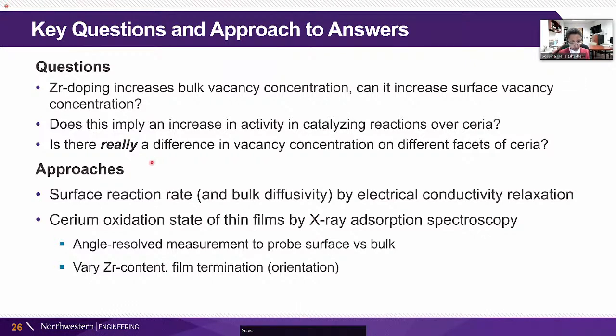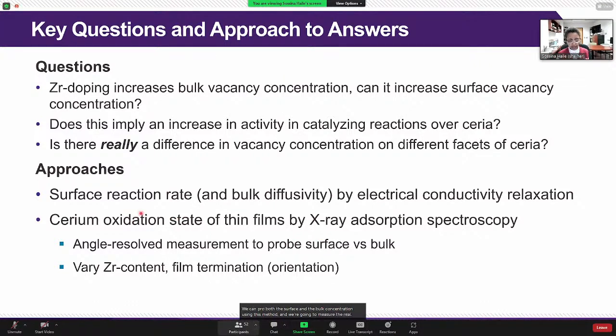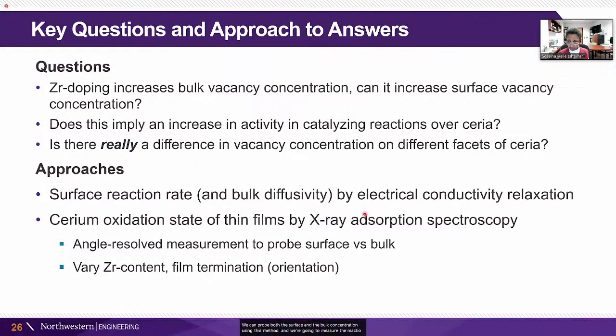So as I said, we're going to try to do the measurement with a somewhat easier technique than these vacuum methods. And the measurement of the oxidation state we're doing by X-ray absorption spectroscopy. We can probe both the surface and the bulk concentration using this method. And we're going to measure the reaction rates and also get the bulk diffusivity by a technique called electrical conductivity relaxation. So let me introduce that macroscopic measurement first.